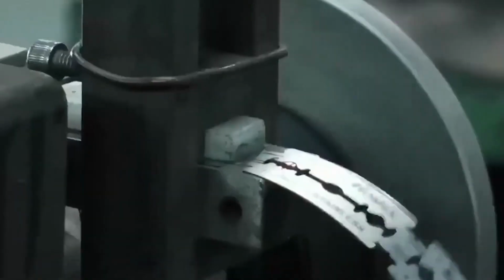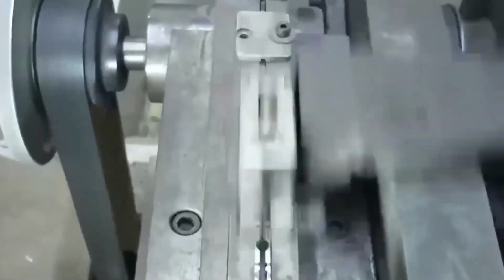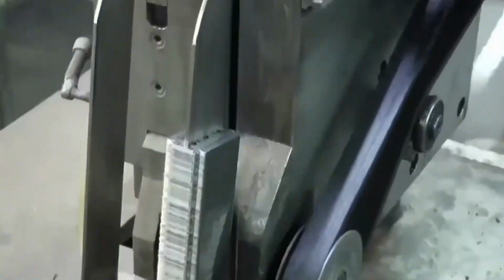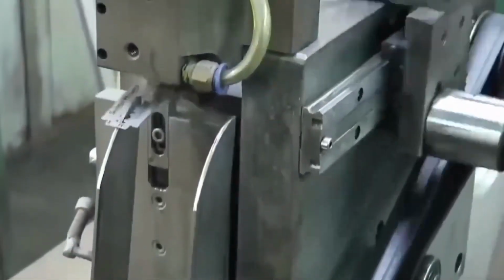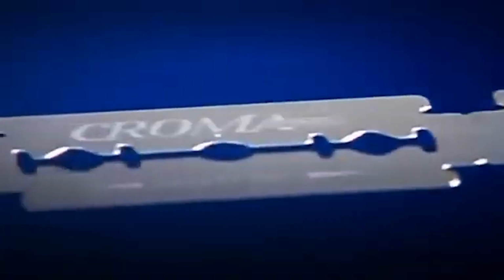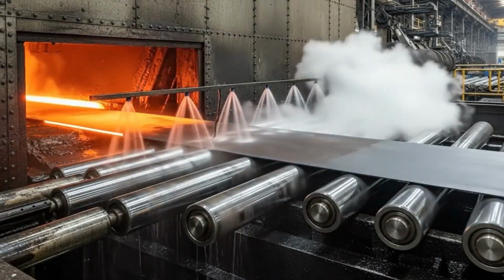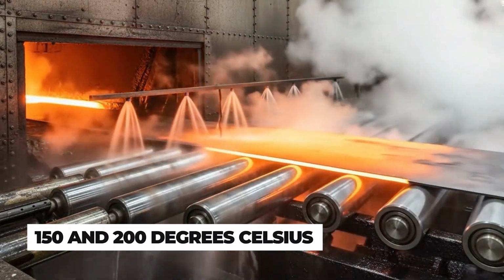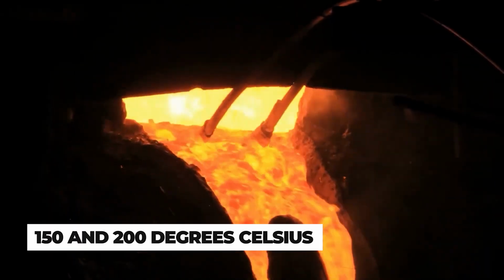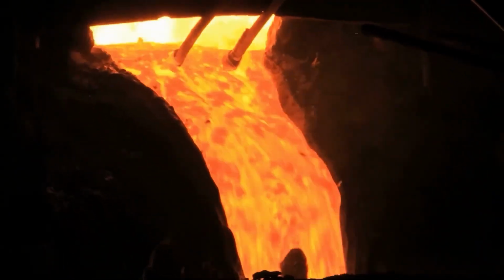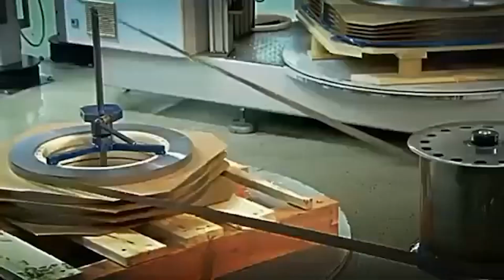Hardened blades at this stage reached Rockwell hardness values between 62 and 65 HRC, extremely hard, but also dangerously brittle. A blade in this condition would fracture rather than flex under the stresses of normal use. The blanks immediately moved into the tempering furnaces, where they were reheated to temperatures between approximately 150 and 200 degrees Celsius for a controlled period. Tempering reduced internal stresses